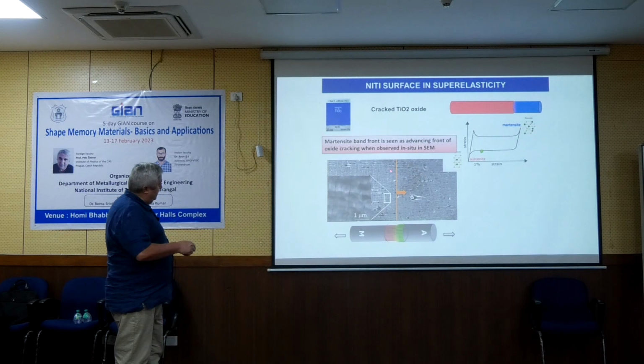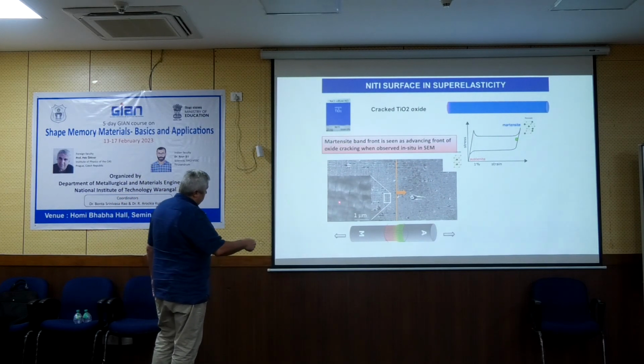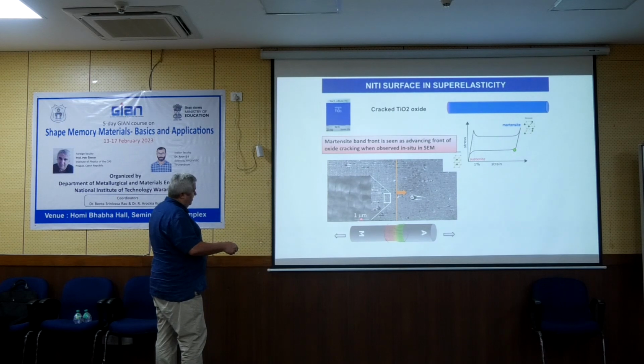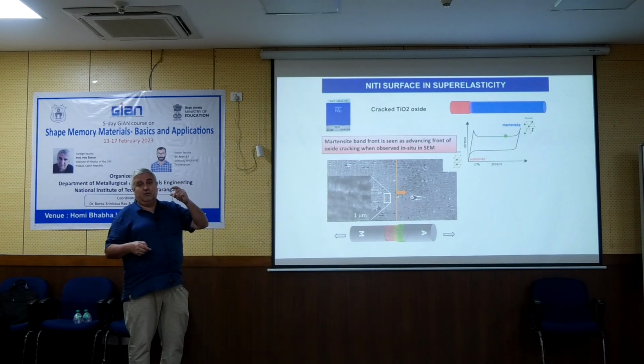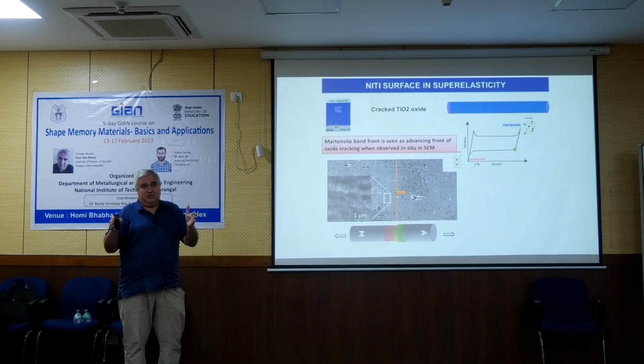So here you can see the same image where under stress there is the moving macroscopic band. Here the oxide is undamaged. Here there are cracks, and there is some periodicity which would be almost like 500 nanometer here. And if you take a different oxide, it would be 100 nanometer. It could be 20 nanometer. It could be 1 micrometer. It depends on the thickness of the oxide. The thicker the oxide is, the fewer cracks you have and more separated, and they are wider.